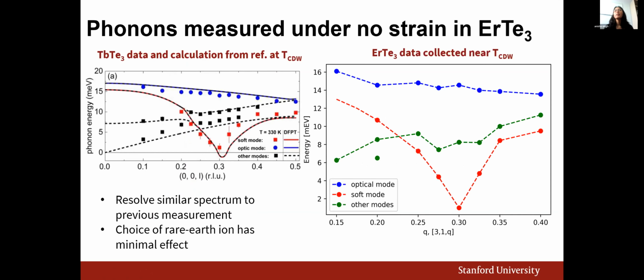Nevertheless, we're still able to extract dispersion of our phonons that is relatively consistent with what is seen for other members of the rare earth telluride family that have been previously measured. No data had been previously taken in this particular erbium telluride, but it has been taken in other materials like terbium telluride and dysprosium telluride. And so we see the general behavior between all of these members of the crystal family is quite similar. So the choice of rare earth ion really doesn't have a large effect on the phonon dispersion.